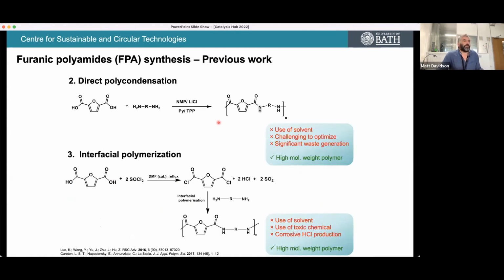You can do direct polymerization, but then you're using solvents. You can make high molecular weight polymers, but it's really not scalable because of the use of solvents. And then things like interfacial polymerization: again, you can make high molecular weight polymers this way, but you're using solvents, and it's really not amenable to an industrial polycondensation of a commodity polymer.